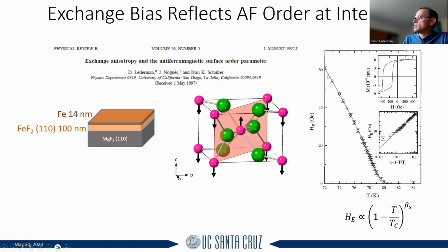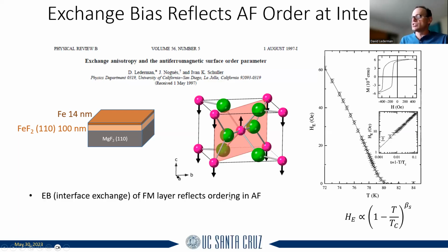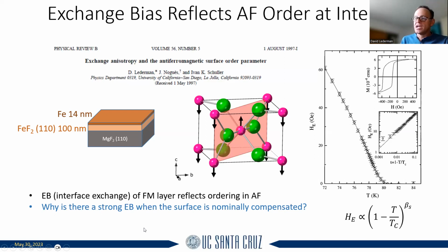The details are actually in this paper, you can look it up. You can see that this solid curve here is a fit to a rounded transition that looks like this. And the critical exponent actually agrees more with a surface phase transition than it does with a bulk phase transition. So this drives the entire idea that this is dominated by an interface exchange effect.